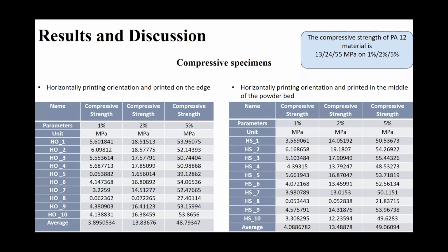The compressive strength of PA12 material is 13 megapascals at 1% displacement, 24 megapascals at 2% displacement, and 55 megapascals at 5%. This slide shows the results for horizontally printed specimens. The specimens were printed on the edge and in the middle of the powder bed.